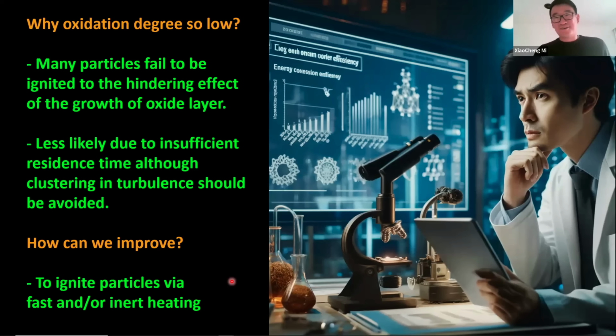Without telling you too much about the patentable content, the scientific message is to try to ignite the particle via fast heating before the oxide layer can be formed, or to have a way to heat the particle in an inert way without letting it be oxidized. And once they are hot, you can inject them into the oxidizing environment. So these are the key features that we think we can do in our combustor to make sure we can get 100% energy to heat efficiency.